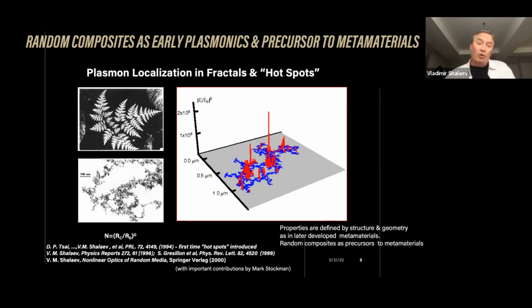And as we showed in our early works, actually long ago, that fractal morphology promotes localization of these collective plasmon excitations. Each small particle supports these plasmon oscillations. Of course, they couple to each other. You have this formation of collective modes, and it turns out they are localized in very small nanometer scale areas, which we refer to as hotspots. And in these hotspots, the local field intensity could be dramatically much higher than the field intensity of incident light, simply because you basically have this accumulated energy in the course of time.